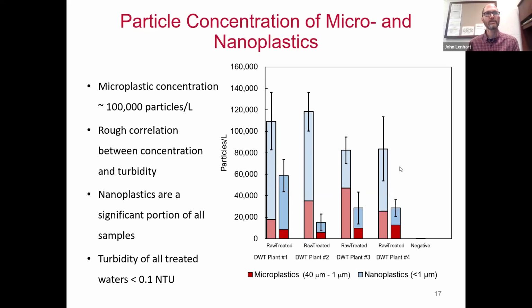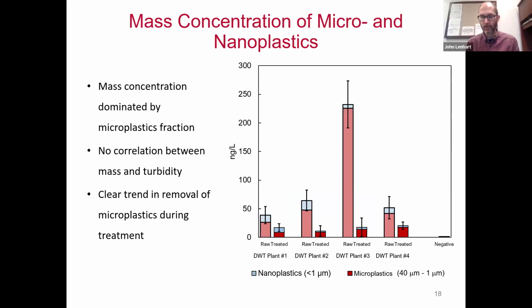The take-home message from this particular set of results is that the raw water from Lake Erie has roughly about 100,000 particles per liter, and there's a fair amount of nanoplastics in the raw water. We see good removal in the treated water, and in the treated water we see that the proportion of the particles that are nanoplastic increases, at least in terms of the particle concentration. One thing to note is that in the treated water, in all cases, this water has had a turbidity of less than 0.1 NTU. So this is, again, treated water, and it's meeting spec. The other way you can look at the data is in terms of the mass concentration. That's what's shown here. Here we've converted the particle concentration to a mass.